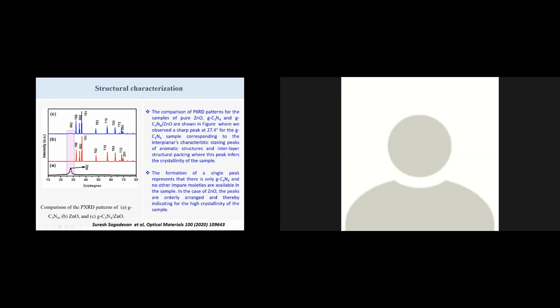So first I'm going to present the fabrication and physical chemical characterization of graphitic carbon nitride with zinc oxide composite with enhanced photocatalytic activity under visible light. You can see here the first X-ray diffraction pattern of this composite, graphitic carbon nitride with zinc oxide composite. You can see here the XRD pattern of A, B, C. A represents the XRD pattern of graphitic carbon nitride, and B is